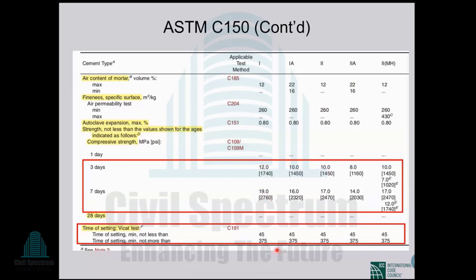Another difference is the setting time. Both initial setting time and final setting time are specified in ASTM. But in EN, only initial setting time is specified. Final setting time is not specified. In EN for CEM1, that is 52.5 strength class, the limit of initial setting time is minimum 45 minutes. Here it is the same. In ASTM, the minimum limit of initial setting time is 45 minutes, but the upper limit is very tight. The upper limit is 375 minutes final setting time.